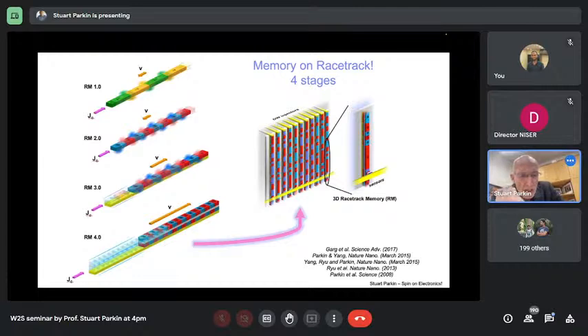And we demonstrated it's because the platinum has a phenomenon called a spin Hall effect, that current passing through platinum will generate a spin polarized current flowing perpendicular to the charge current. And this spin current then can flow into the racetrack and apply torques on the domain walls. And then they will move, and they will move very efficiently.